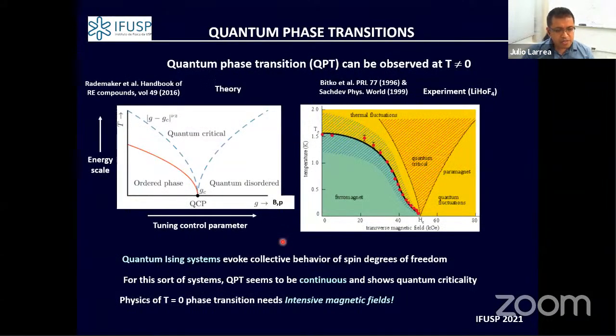And it's not only an idealization from theory, but it can also be found in experiments—this kind of quantum phase transition exists, in particular for a system realized in lithium holmium fluoride. You can see, for instance, that this system is ferromagnetic, going from a paramagnetic state to a ferromagnetic state around a Curie temperature of 1.5.